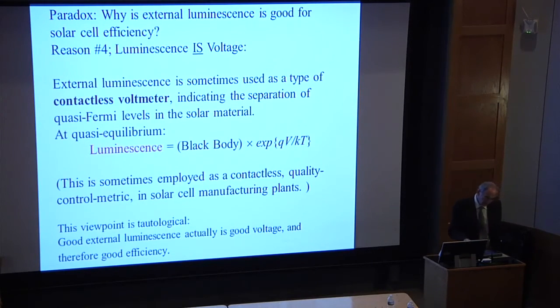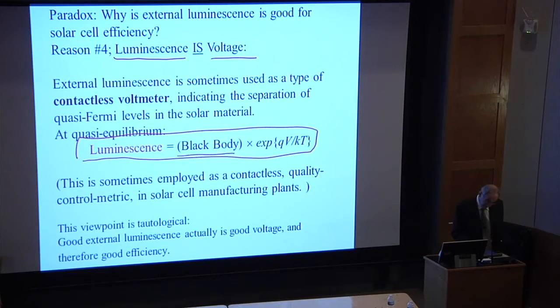So reason number 4 is that luminescence is voltage. Now there's a formula, and you can just derive this from thermodynamics, that luminescence is the Planck black body radiation multiplied by the internal voltage. Everything that's excited has an internal voltage, even if it's not a semiconductor, even if it's a dye molecule, there's an internal chemical potential associated with the excess excited states. And so there's some kind of a voltage, and that can be derived thermodynamically. So what it says is that, yes, sure, go for luminescence because that means you have more voltage. But maybe that's not completely obvious.